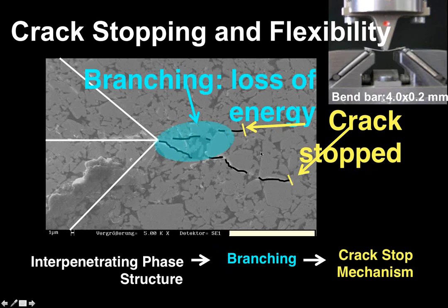And this is a similar effect that you see with zirconia, where we have our transformation toughening taking energy away. So even though you may have a defect in your material under stress, under natural use in the mouth, the crack doesn't go all the way through it, and then we don't have the catastrophic failure of the patient calling you at 10 o'clock at night. They have some event to go to the next day. They just bit down on something and their ceramic crown cracked in half. That's a catastrophic failure. You won't tend to see that with materials like this, which can stop the cracks from propagating through the material.